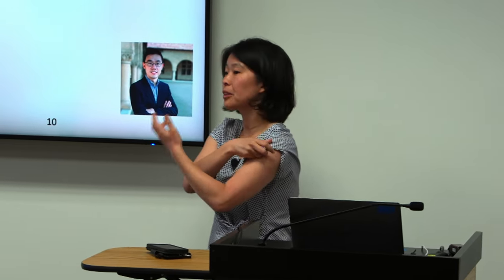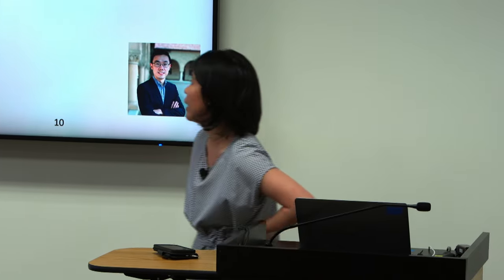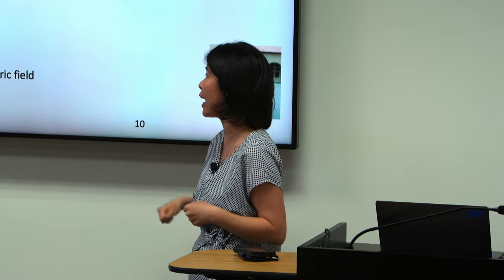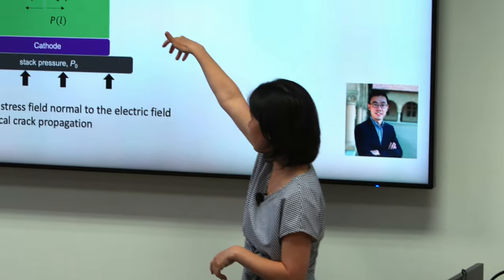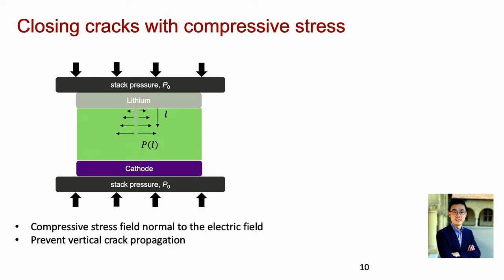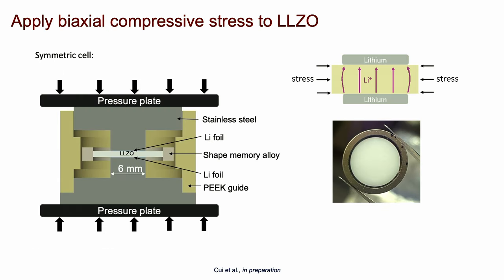So again, coming from the mechanics point of view, when we see cracks form, all of mechanics is actually very intuitive. If you're having cracks form in this direction, what you do to stop that happening is push it from the other direction, right? So close those cracks. This is a schematic of the battery where you have lithium, the solid electrolyte, and then the cathode. What we would need to do is envelop the solid electrolyte from the sides to push those cracks closed. Tung is a postdoc working with me, and probably this isn't the first time someone thought of this, but he thought of this really clever way to make this happen.